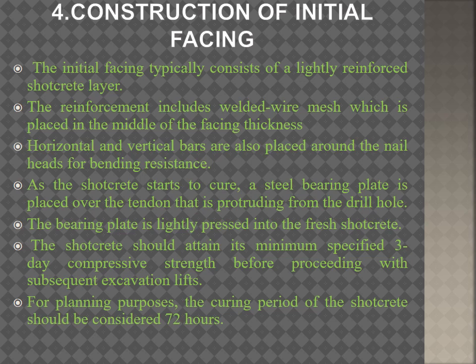Step four is construction of initial facing. Before the second lift of soil is excavated, an initial facing is applied to the unsupported cut. The initial facing typically consists of a lightly reinforced shotcrete layer. Reinforcement includes welded wire mesh placed in the middle of the facing thickness, with horizontal and vertical bars placed around the nail heads for bending resistance. A steel bearing plate is placed over the protruding tendon and slightly pressed into the fresh shotcrete. The shotcrete must attain its minimum specified three-day compressive strength before proceeding with subsequent excavation, with a curing period of 72 hours.